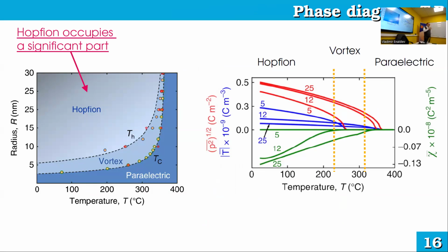so you already asked a question about the size of particles. So we plotted a phase diagram, temperature versus size of nanoparticles. As you can see, Hopfion occupies a significant part of this phase diagram. I already told you that vortex is also a stable state near the temperature of phase transition. And for particles smaller than around 3 nanometers, we have a paraelectric state. Also, temperature only appears in the Landau free energy in alpha 1.